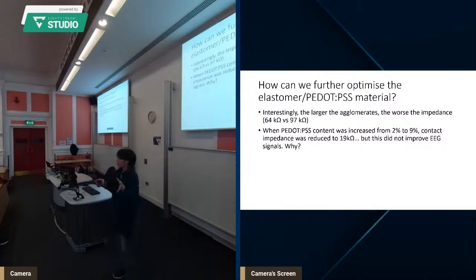The signal is worse because of this lateral movement of the signal. Also, when we increase the PEDOT PSS content from 2% to 9%, contact impedance improved. So the lower the contact impedance, the better. At a higher concentration of PEDOT PSS, the impedance was reduced to only 19 kiloohms. However, even though impedance was reduced to 19 kiloohms, this did not improve the EEG signals.